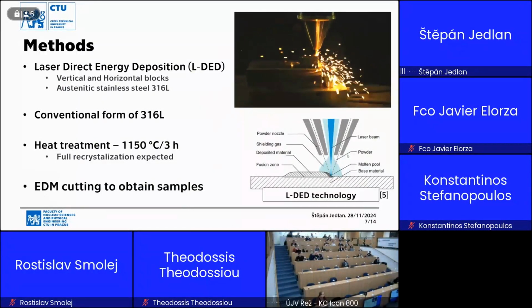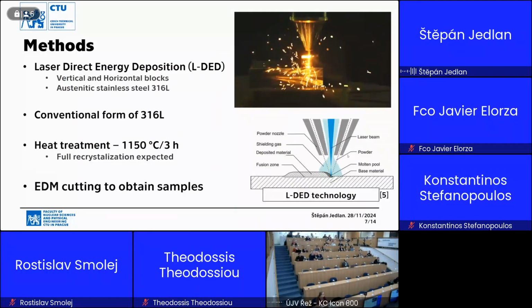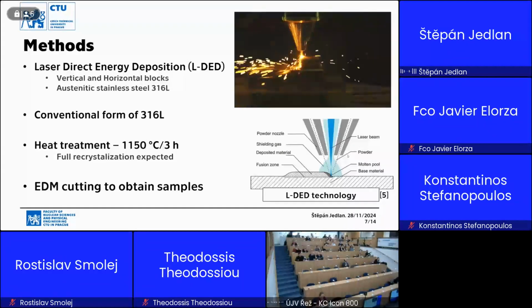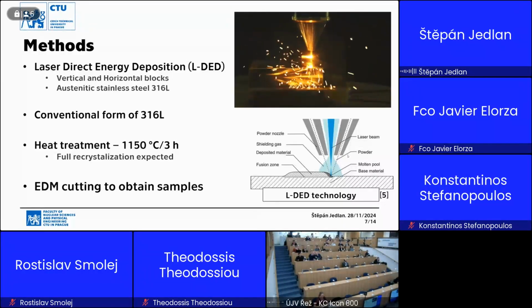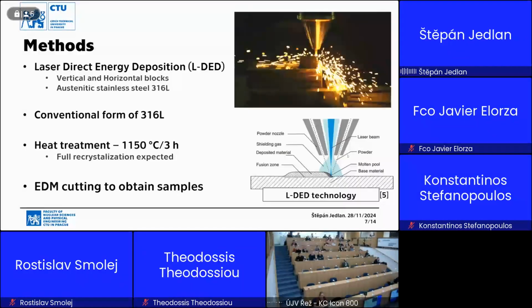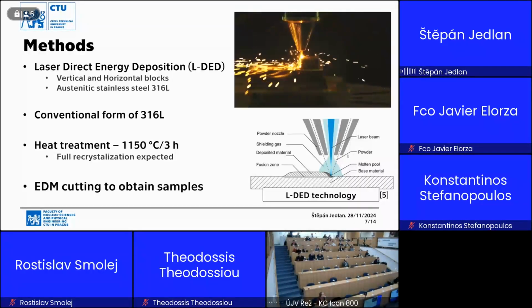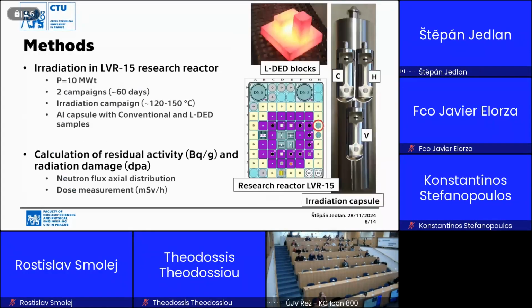On the right side, you may see the LDED technology, which is basically the same as fused deposition for plastic, but this one uses wire or powdered material. In this case, powdered material comes through the nozzle, the laser goes through a nozzle too and melts the deposited powdered material on the substrate. Once the first layer is printed, the nozzle goes up and prints another layer. Now the samples were obtained through EDM cutting, and you can see those samples on the right side of the slide. There were about 20 from each type of material, which means horizontal, vertical, 3D printed, and conventional.